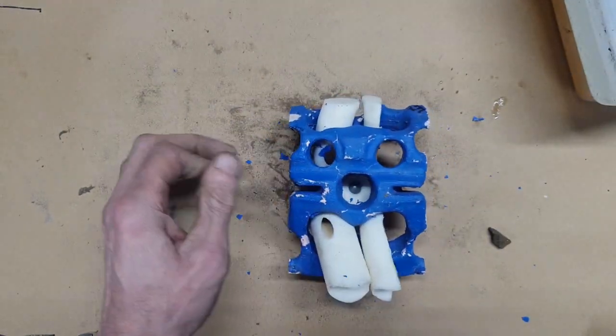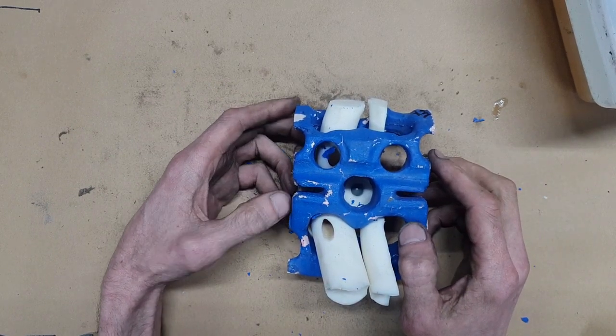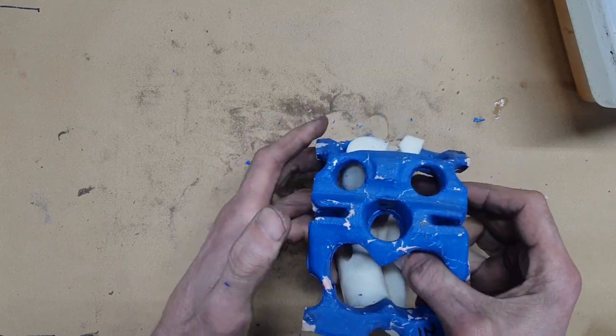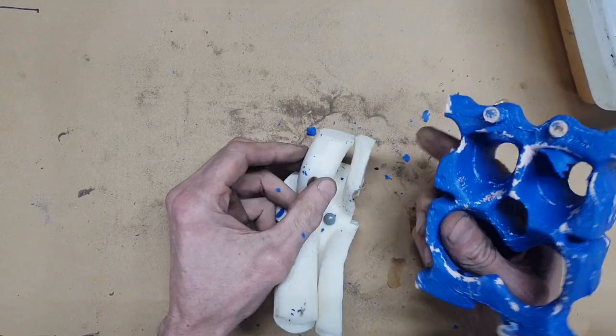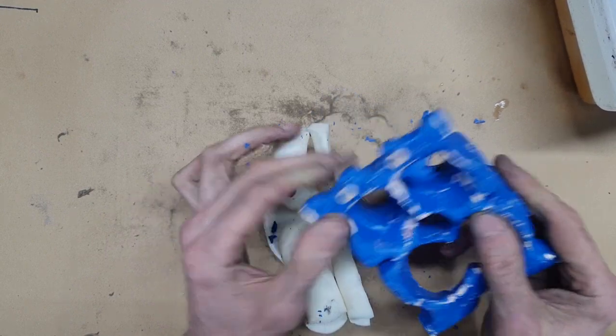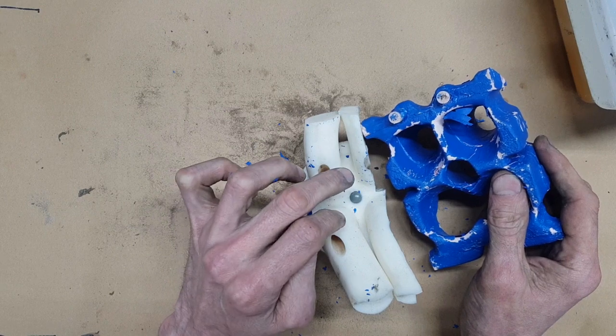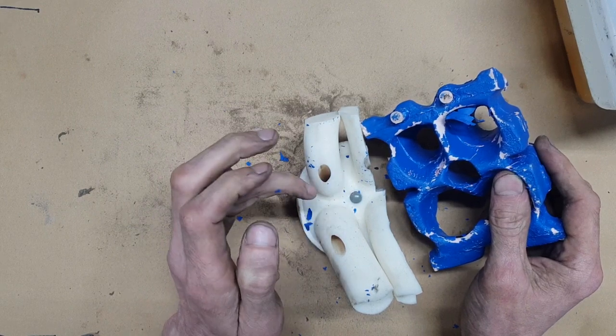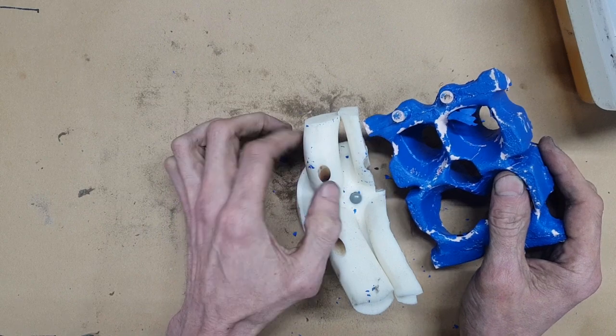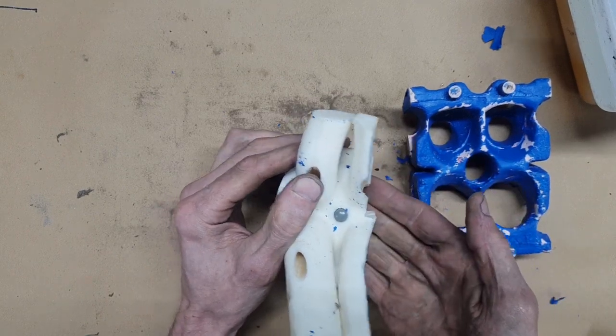So with the new idea that they came up with, that company I mentioned a minute ago, which I won't mention again because I can never think of it, Southwest Research, they devised a method of making a really thin core, as mentioned. Now this had two effects. It got rid of the huge mass of aluminium here, which they had to have because they couldn't make the core so small, it'd be so fragile. So that resulted in a reduction of tearing, hot tearing it's called, where one metal solidifies before the other. Hot tearing issues were reduced, and they could also then make these areas a lot smaller here, which meant they could support the combustion chamber more.